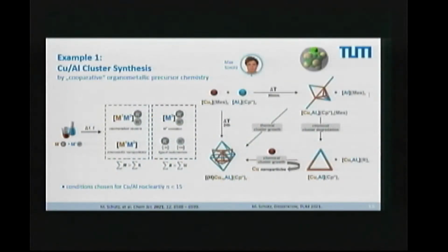Two things can happen. We can get intermetallic clusters, or we can get intermetallic nanoparticles. What's the difference of the cluster and the nanoparticle? Now the cluster is a finite atom object, maybe 10 atoms, 20 atoms, 50 atoms of two different metals together. A nanoparticle is something of 500 atoms, 1,000 atoms, 10,000 atoms. So the same chemistry, the same precursors may give us discrete clusters or nanoparticles, depending on the conditions. It's interesting to get the nanoparticles as well, and we have done it. And we can do catalysis with the nanoparticles in colloidal solution, making them by the same chemistry.